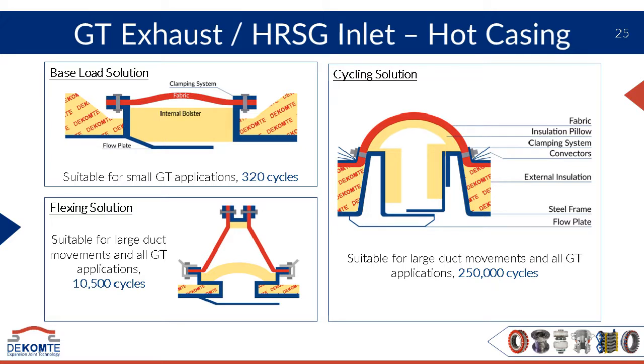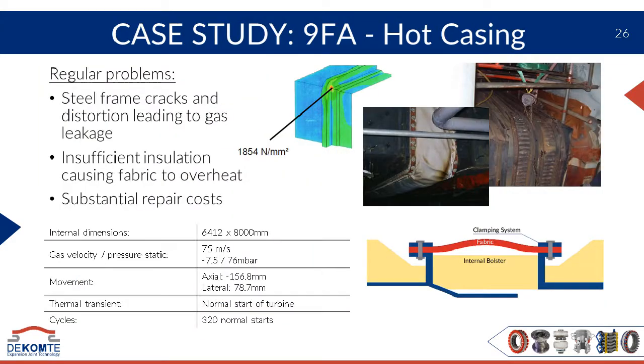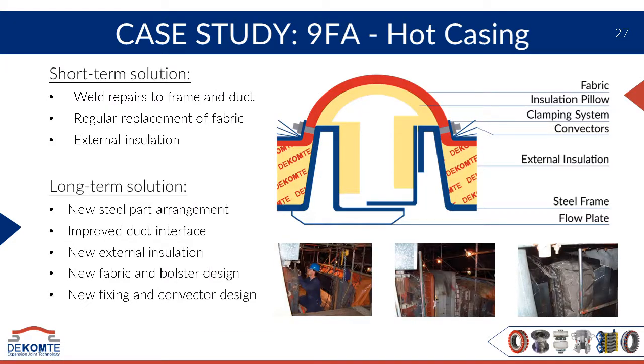material. So the key point in these is that if we need more cycles, actually the first thing that's really changing is the whole steel frame assembly. This design needs to significantly change. Just to show a few examples of that in place, square ducts are the worst because the corner acts as the stress concentrating point where the frame cannot rotate or buckle to relieve its stress. And you can see on the burnt portion of the expansion joint on the photo there that the heat is coming up from the inside of the frame as the deformation of that pillow is also showing. So lots of cracking. Lots of heat damage causing the failure of these expansion joints.